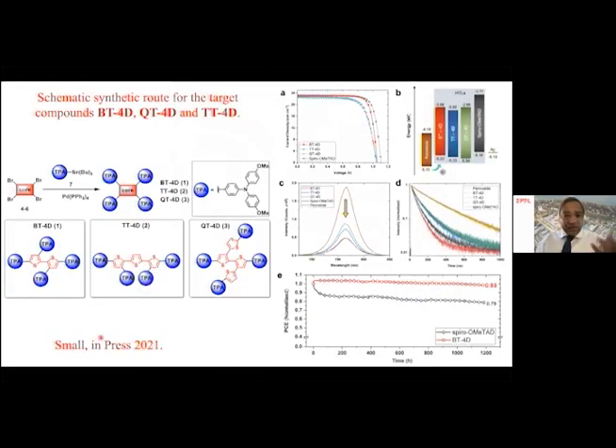Followed by, again, the same motif, we have thiophene groups with the donor groups. So here, this is our recent work, which appeared in the press. When we use this type of hole transport materials, the efficiency remained after 1,200 hours; the decrease in efficiency is less than 2%. So this is the beauty of this new class of hole transporting materials which we have developed. This work appeared in Small.